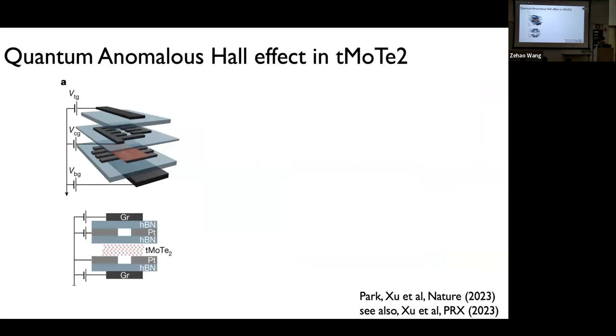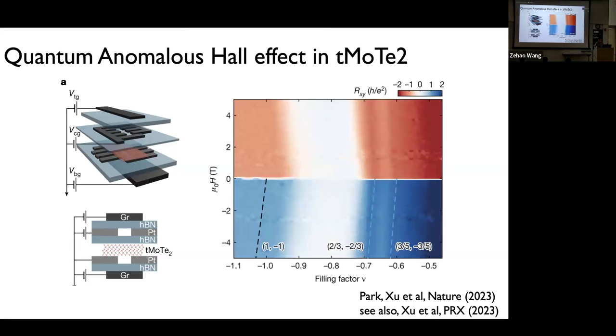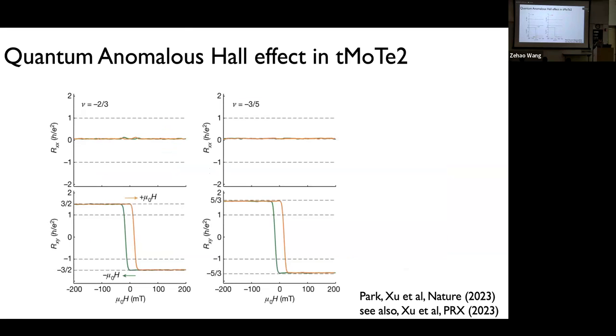And of course, the most direct evidence comes from transport measurement, if you can measure Rxy. I just want to mention that this is highly, highly non-trivial, because a transition metal dichalcogenide is hard to make contact with. In this device geometry, they had to, for example, add another layer between the top and the second transparent layer, which is the boron nitride, because you need an additional layer of gate to gate the contact, so that you can allow current going from your electrode to the sample and then reach the other side. I will skip this. The bottom line is that they saw hysteresis, which is smoking gun evidence of fractional quantum anomalous Hall effect, or 0 field FCI.